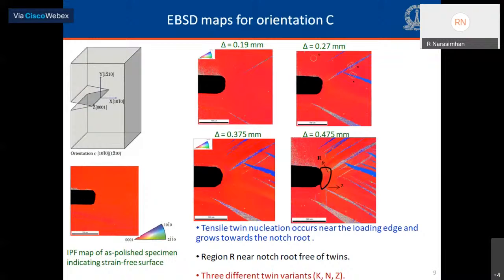But here, let me turn to the other orientation, orientation C, where the C-axis, as you can see in the schematic, the 001 axis is along the direction of the notch front, that is along the thickness direction. Again, taking a look at the IPF map of the as polished specimen at the bottom left side, you can see a strain-free surface in this case. And then examining the sequence of IPF images on the right side corresponding to different load point displacements, we can see a different pattern of twin development which is taking place.